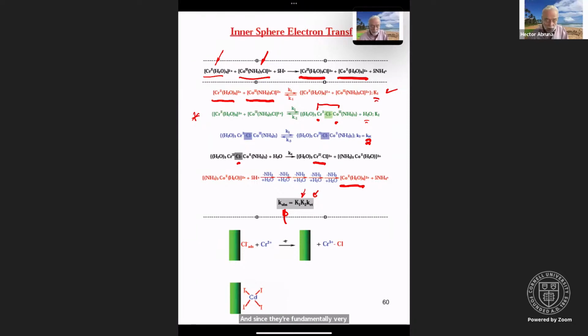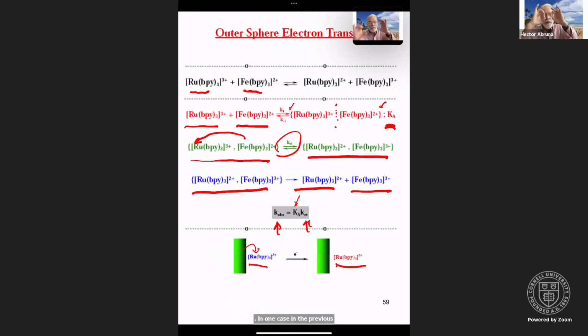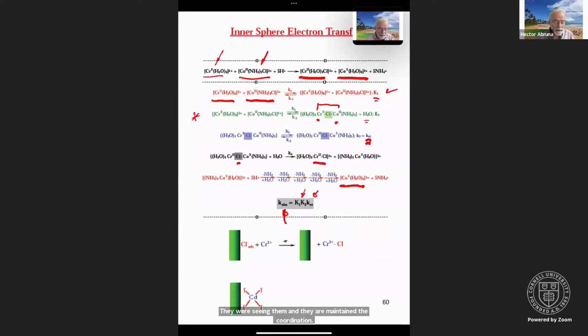And so these are fundamentally very different processes. In the previous case, if we go back here, it was like two spheres coming together, electrons get exchanged, everybody goes their merry way. The ruthenium and the iron maintain their coordination geometries. In this case, you start with hexaquo chromium 2 and pentaamine chloro cobalt 3. Upon electron transfer, you end up with chromium pentaquo chloro, chromium 3, and hexaquo cobalt 2.